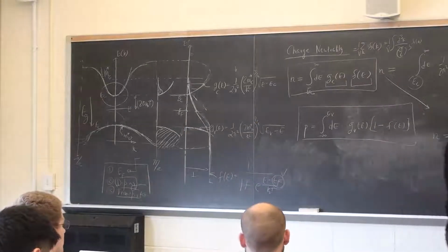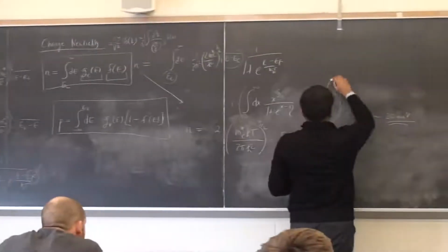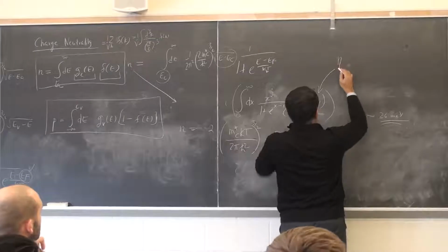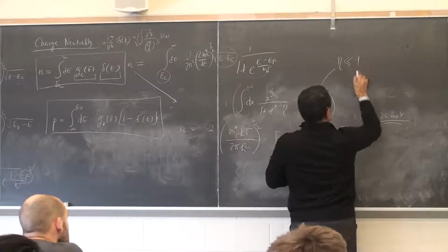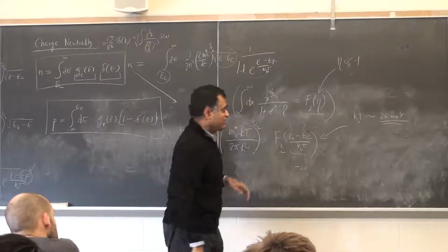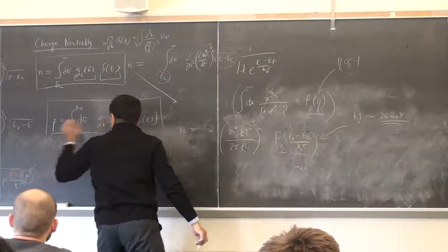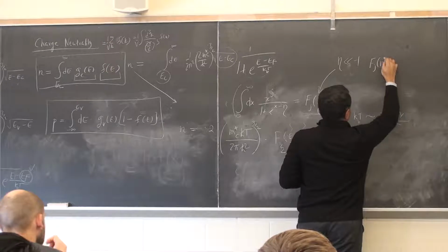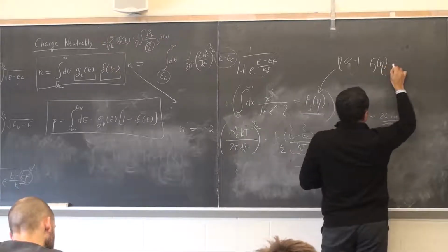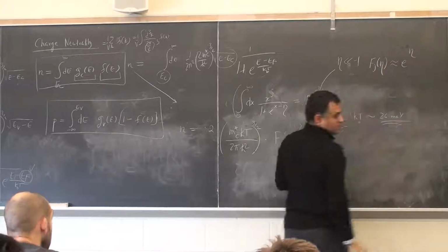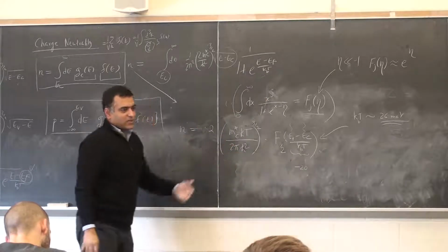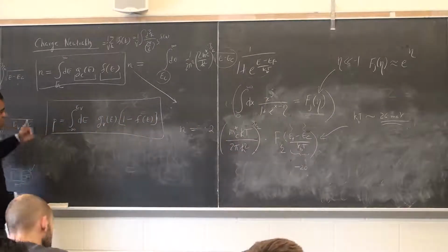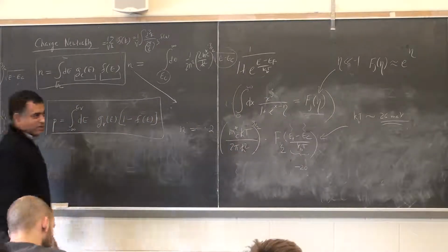So this function, the Fermi Dirac integral, has a very nice approximation: if your argument is much less than minus 1, and you can kind of see that right here, then the Fermi Dirac integral of any order j becomes e to the power eta. This is the Maxwell Boltzmann approximation of the Fermi Dirac integral. It's a very, very useful approximation.